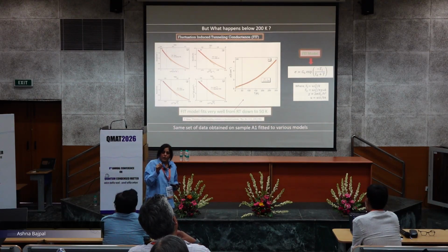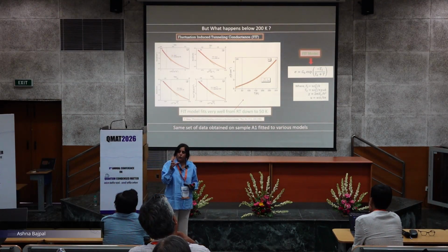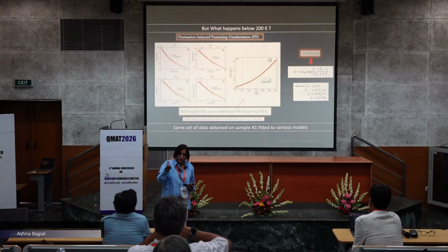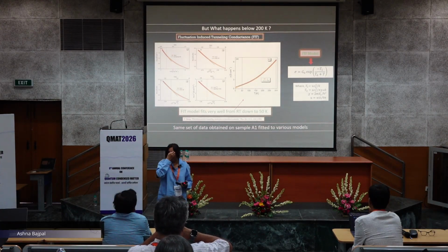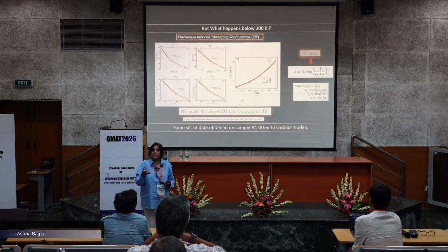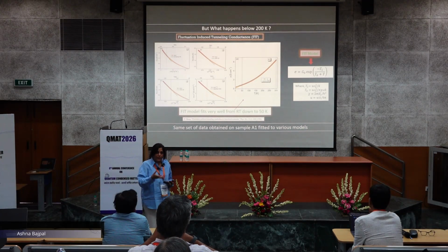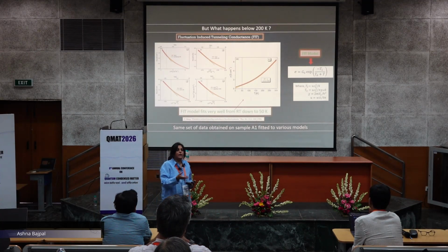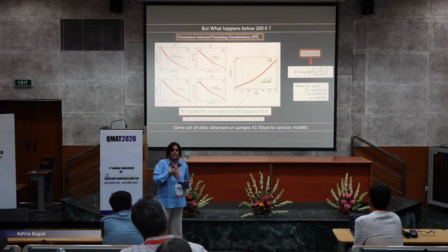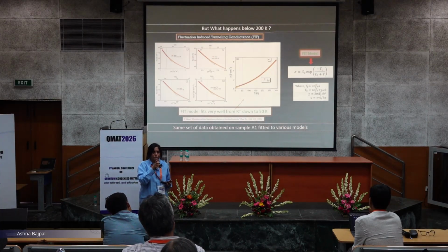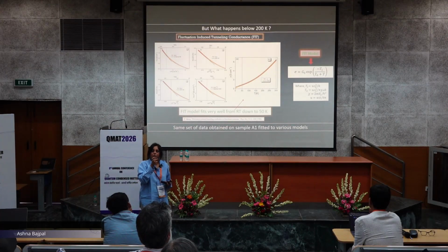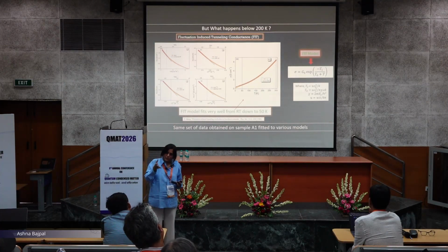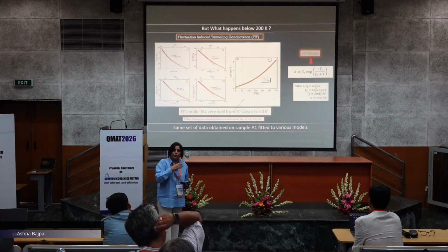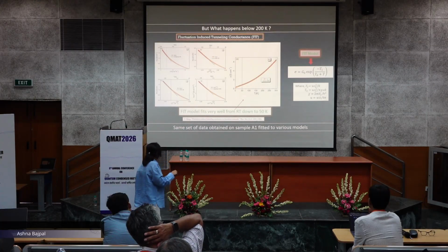And not only for mesoscopic conducting grains with insulating surface layer, this model seems to describe highly disordered semiconductors very well, where VRH and Arrhenius do not fit. So conducting carbon spheres, tunnel junctions of conducting material with silicon oxide coating, and so on. In all these cases, this model works.